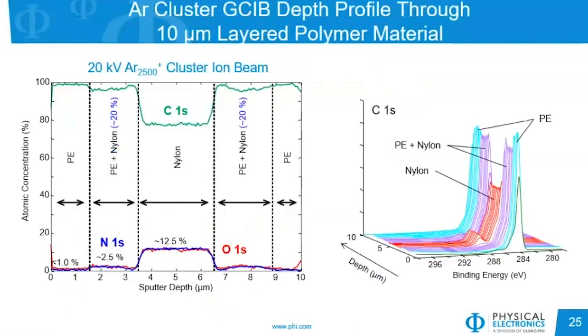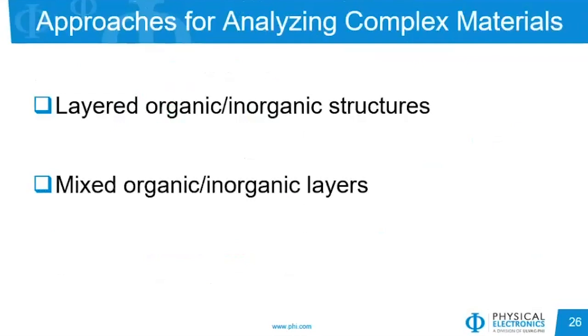As shown here, this is a blended polymer of polyethylene and nylon, multi-layer structure, and we can sputter through up to 10 microns and beyond while maintaining the chemical structure of these two materials as well as their composition and stoichiometry. With that, we have talked about inorganic materials by themselves, organic materials by themselves, but a lot of advanced structures that we see now combine both of those, either in layered methods or actually in combination in a single phase. And so how should we approach these complex materials that we tend to see more of in our research?